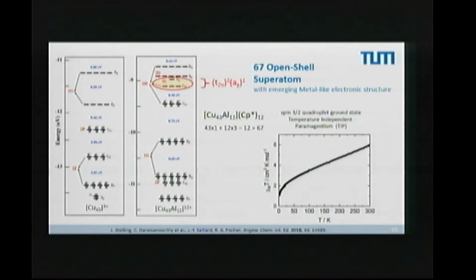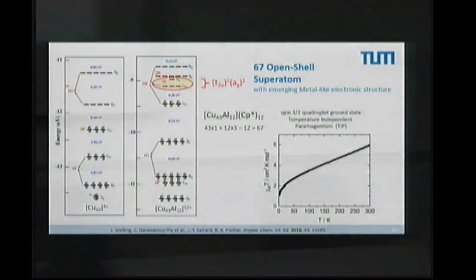What is more interesting is the electronic structure of this whole system. Just look at these energy levels, and it's a little bit sophisticated to do the calculation. This has been done on a copper 43 aluminum 12 plus entity, leaving away all the hydrocarbon ligands and coming up with this kind of level splitting. So what happens here is that in the LUMO section of this cation, so to say, we have a situation where 3 orbitals are here and 1 is coming very, very close. This is the 1H and the 3S superatom orbitals. And in the neutral compound, where we have the hydrocarbon ligands put on, these levels accommodate 3 electrons. So it's a 67 electron open shell superatom in this case, and they have a paramagnetic ground state with 3 unpaired electrons. We can measure that with